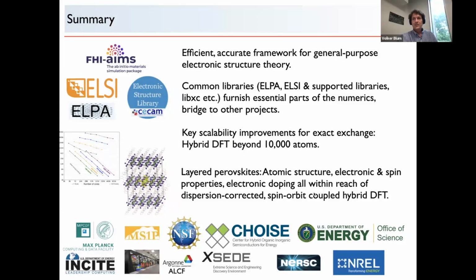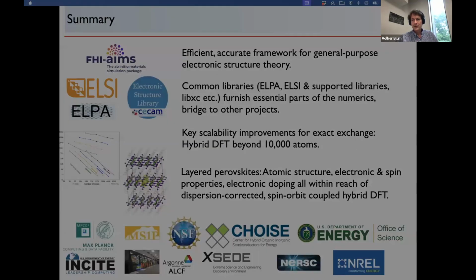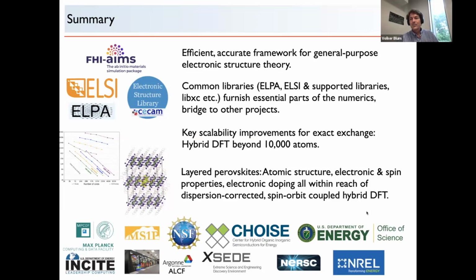So this is a very good question, and the answer is, first of all, very simple, but it's a great question nevertheless, because it's a frequently asked one, and it's important to keep that in mind. We can, of course, no problem include the van der Waals correction into HSE, but we use the HSE here for a different observable. So for the perovskites, we use PBE and a dispersion correction for the structure.